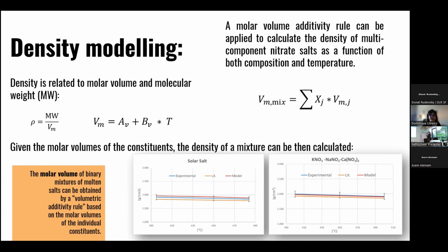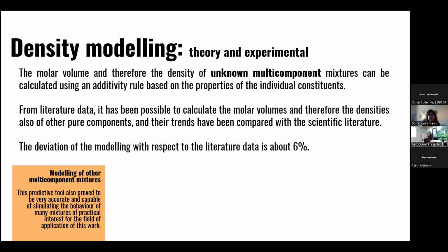And I reported only some results that we obtained for all the mixtures that we measured. As you can see, the experimental data, that is the blue line, compared to the literature data and the modeling, is quite accurate within the experimental error. So we decided that it was a good approach.